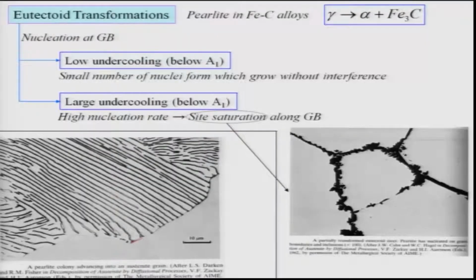This is the interface, this is the gamma, and that interface is between gamma and the reaction product. The reaction product is obviously alpha and Fe3C, this is Fe3C as you see here. So what you see here, as the interface moves, both the phases are growing together. That means this is a cooperative growth.